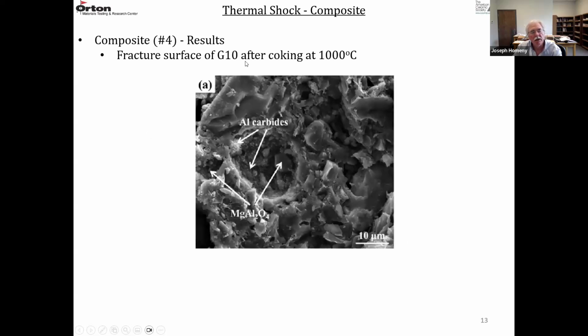And this is G10 after coking at 1,000 degrees C. So G10 again had no MgO carbon pellets. The X-ray diffraction picked up some spinel, MgAl2O4, and an aluminum carbide. So they're just pointing out where these minor phases are located. They're using EDS to figure out what the chemistries of these different features are. And if the chemistries match up to spinel or a carbide, they can identify it.